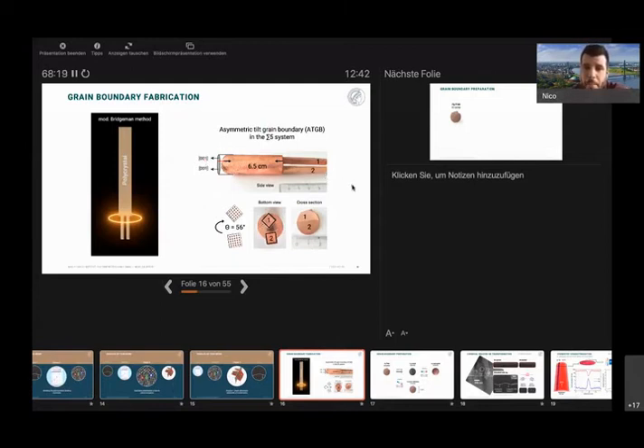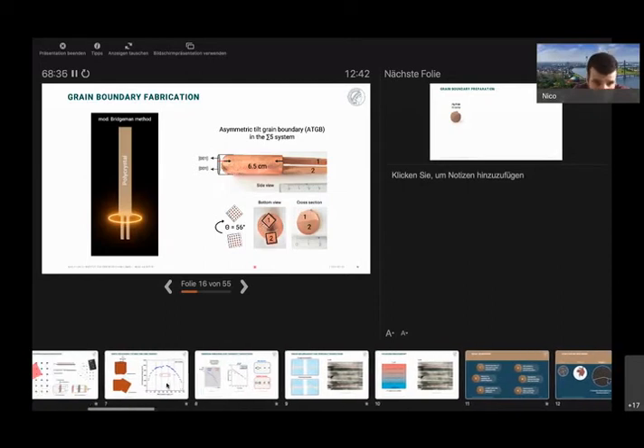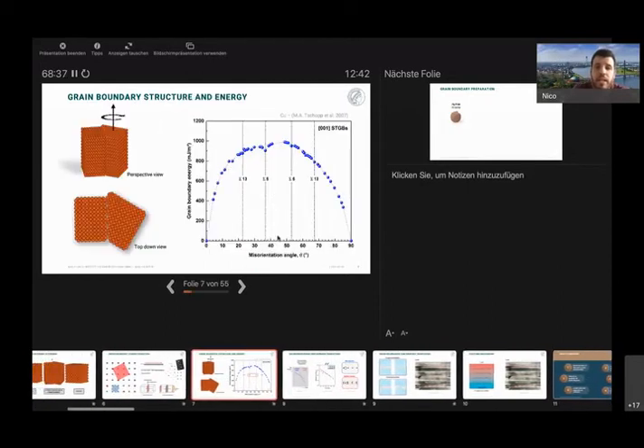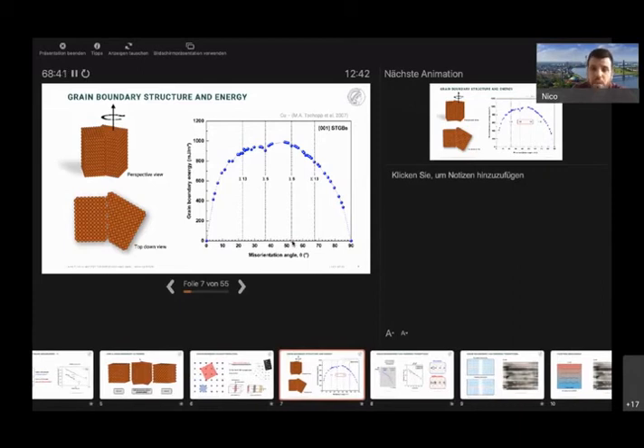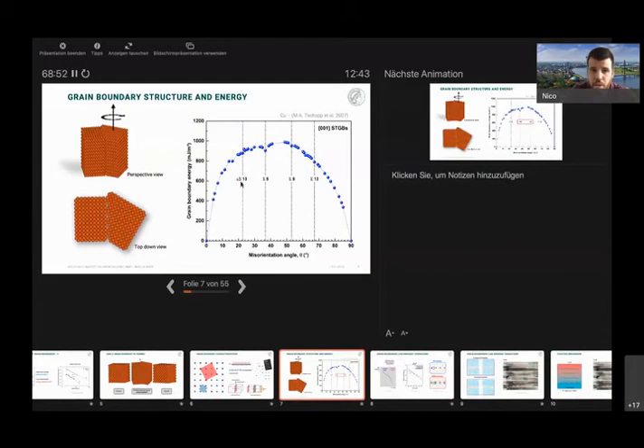Okay. So you are orienting this 54 degrees beforehand, means two seed crystals at 54 degrees, and it's actually forming the sigma 5 boundary. Exactly. So if you go back to this graph here, the 54 degrees orientation here, that's the sigma 5 orientation. If you would rotate by, let's say, 20 degrees or 22 degrees, you would probably form a sigma 13 boundary. Okay. Does that make it clear?